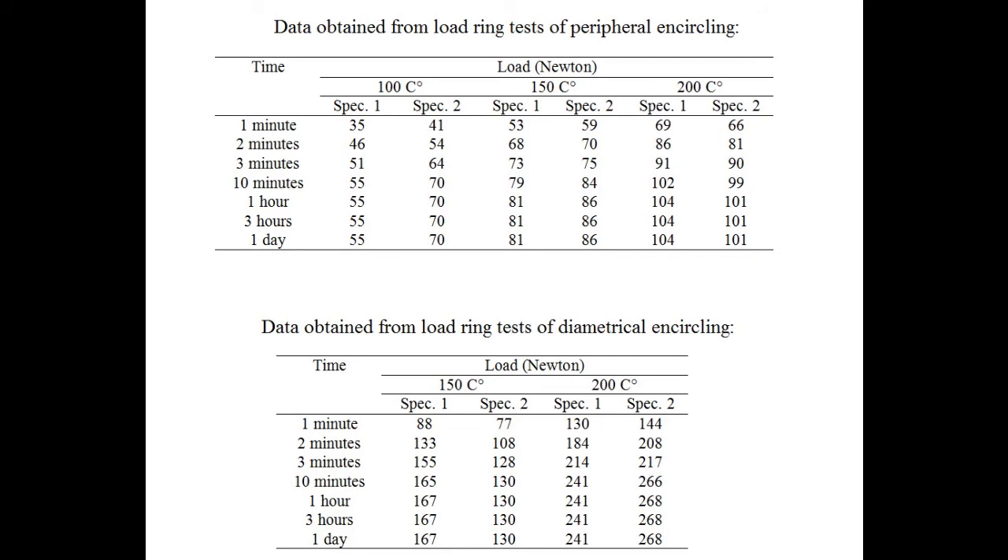The results of heating in the stove at 250°C confirm that polyamide ties cannot retain their original length after the heating process and lose their strength and ductility because of degradation resulting from excessive temperatures.